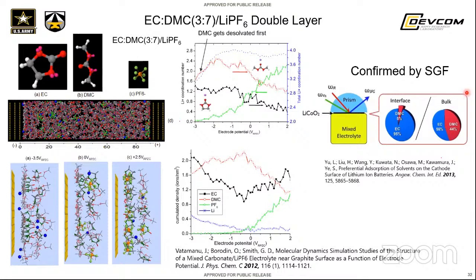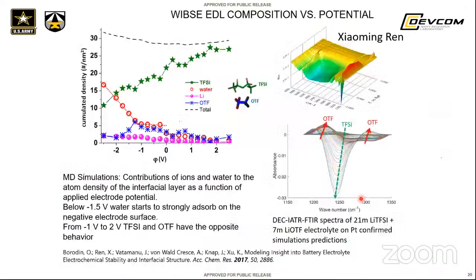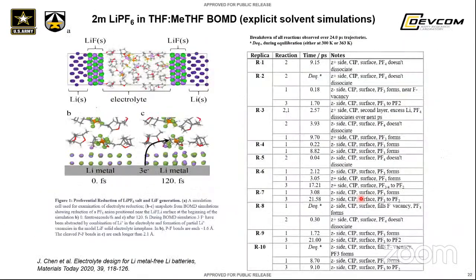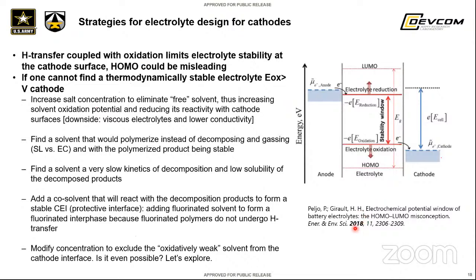But okay, first of all, I had a remark which I put into the chat with respect to the stability of electrolytes. I don't know whether you came across the paper of Peljo and Girault from 2018, which impresses that it is a misconception that the HOMO-LUMO gap really determines the stability; it's rather the electrode oxidation potentials. The simplest example, which you all should be aware of, is water. Water has a HOMO-LUMO gap of 9 eV, and it has a stability window of 1.23 volts. So in principle, I always tell my students, don't believe everything that a Nobel laureate says. It can be really nonsense, so to say.